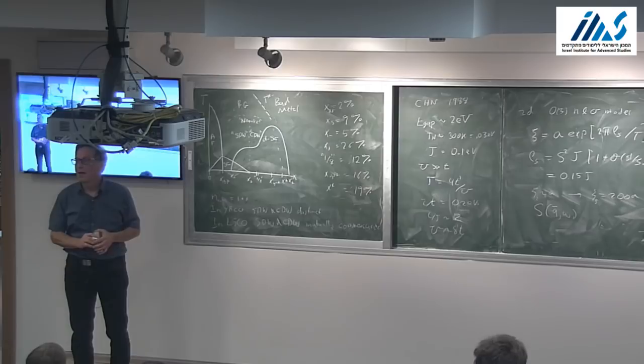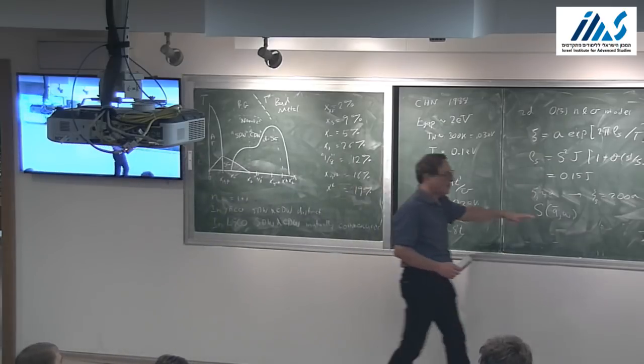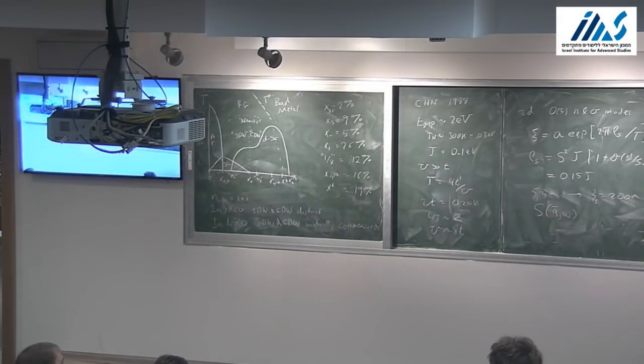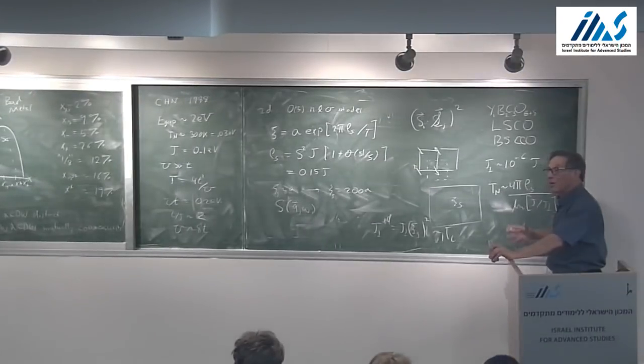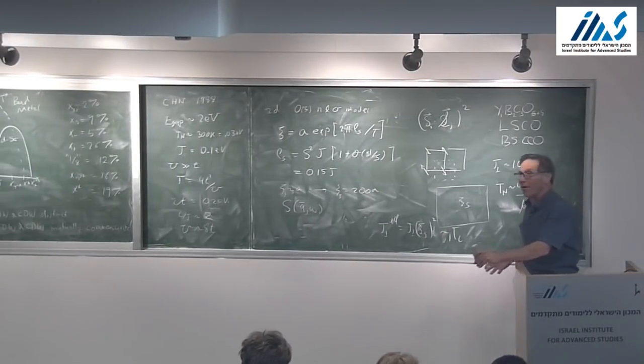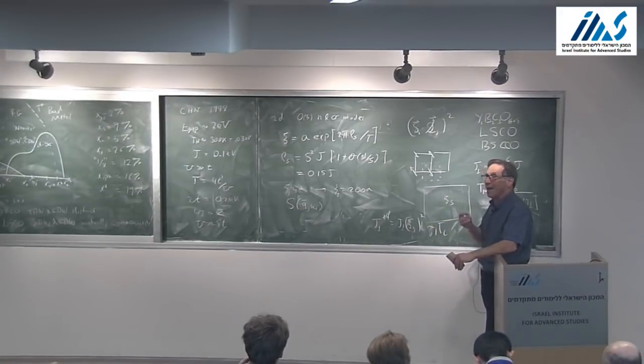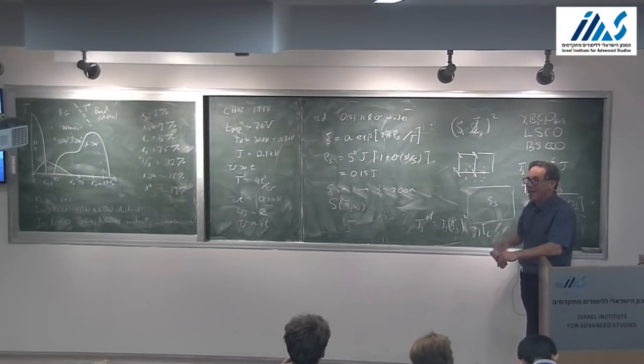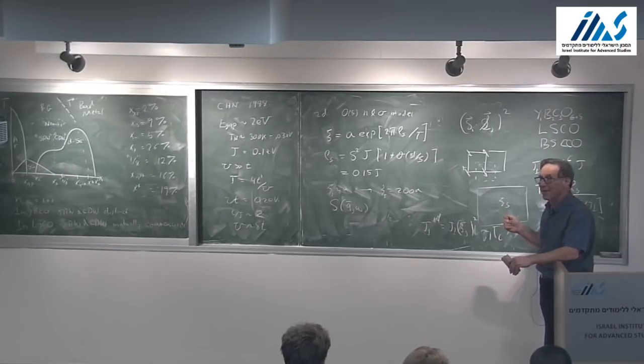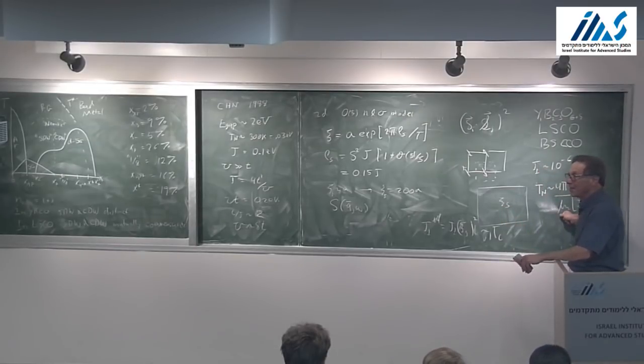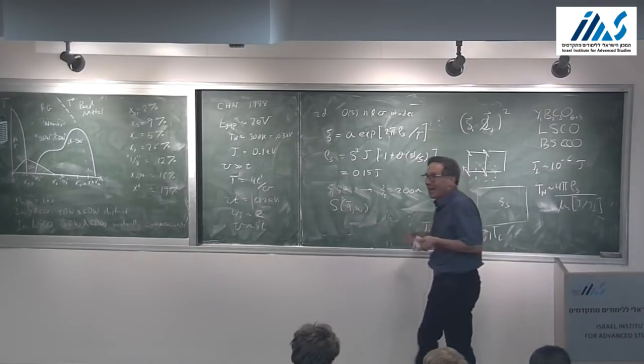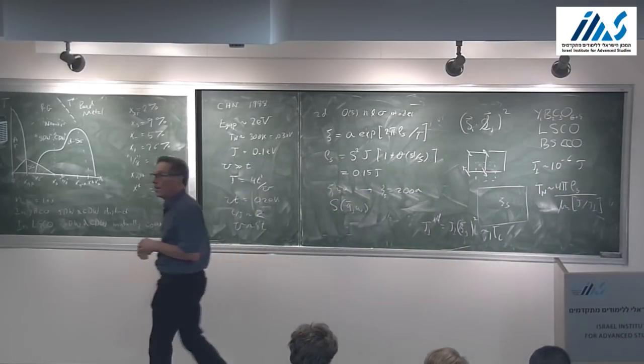Yeah. So I guess essentially you're saying that if you have order in multi-dimensional systems. Correct. But the thing that's striking is, if I told you that this coupling is 1,000,000 times smaller than the couplings we're keeping, you would say, okay, until I get down to astronomically low temperatures, who cares? But all that comes in is the logarithm of this. So even though that's 10 to the minus 6, the logarithm of it is 14.